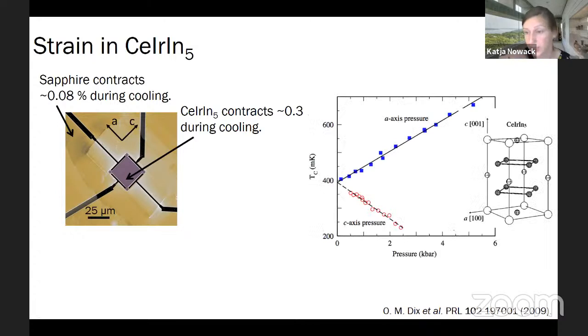And it is known that the critical temperature of CeIrIn5 is sensitive to strain. This, for instance, can be measured on bulk single crystals using hydrostatic pressure measurements. If you press the crystal along the A-axis, which is an in-plane axis, Tc goes up. If you press along the c-axis of the crystal, then Tc actually goes down.